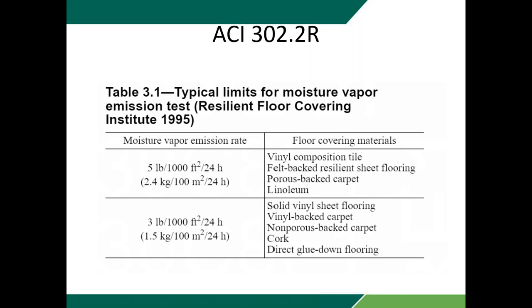Now, I would point to the fact that this study was done in 1995. So it's getting to be a little dated, and it was probably done right around the time that the EPA was instituting the regulations that were changing the adhesives. So some of these categories, like vinyl composition tile and linoleum and things like that, have probably dropped down into the 3 pounds per 1,000 square foot limit rather than the 5 pounds per 1,000 square foot limit. But needless to say, this document does a good job of spelling these things out for us.